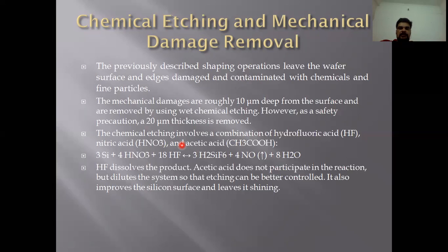These mechanical damages are roughly around 10 micrometers deep from the surface. So certain chemical processes are done so that these can be removed. The damage is basically 10 micrometers deep from the surface of the wafer, but for the sake of safety, 20 micrometers thickness is removed from the surfaces by a chemical etching process. The chemical etching involves a combination of hydrofluoric acid, nitric acid, and acetic acid. So this is the reaction that takes place here.